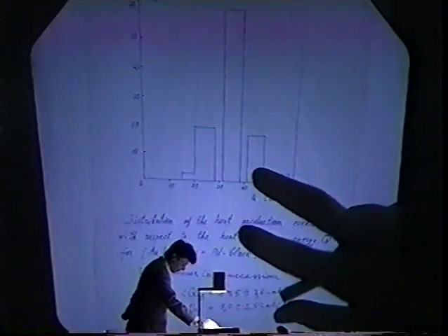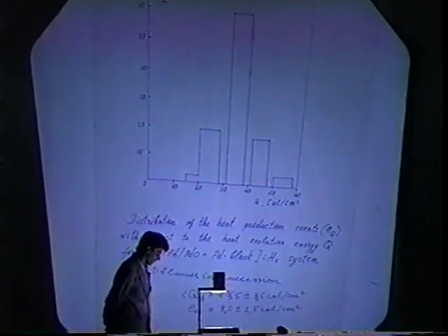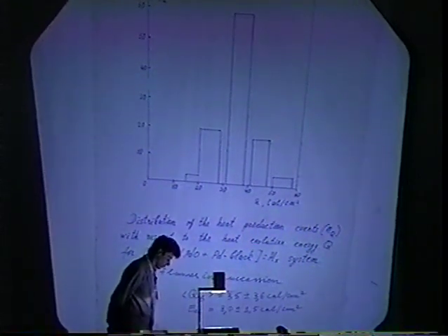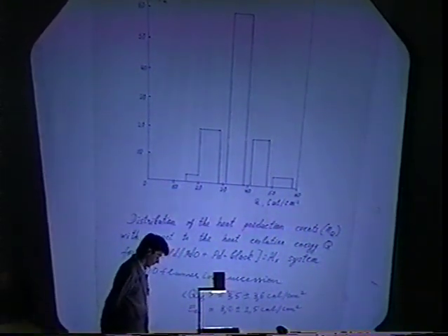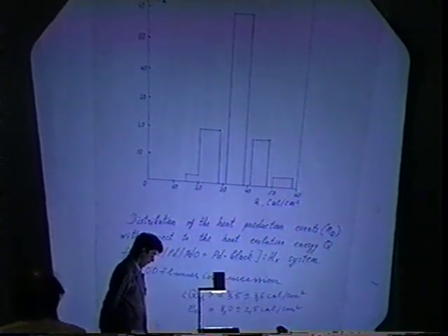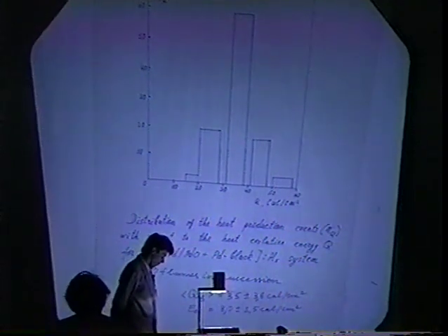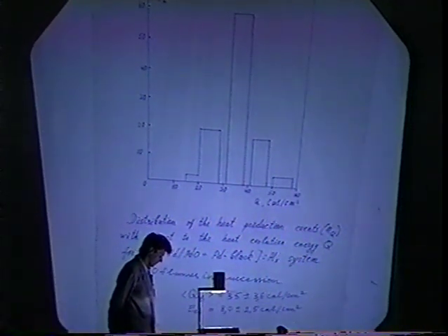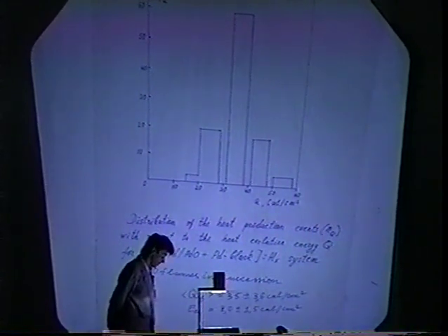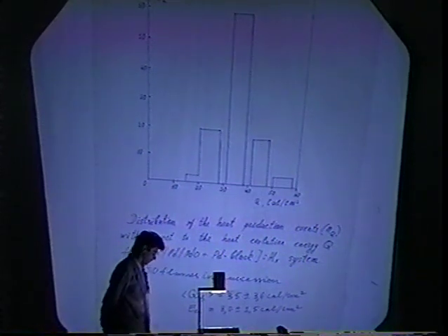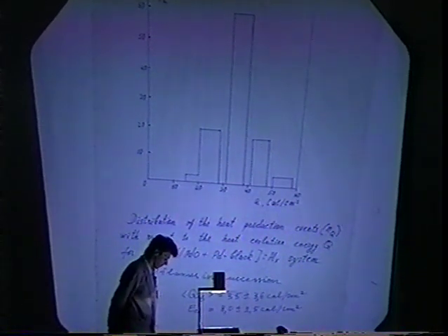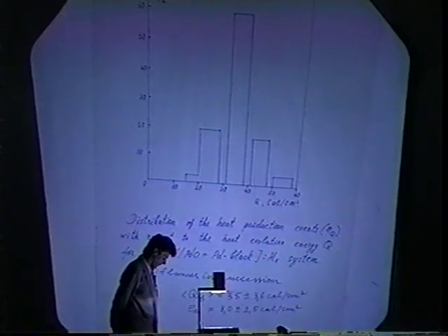The magnitude of the thermal effect can be increased essentially when the specific surface of the heterostructure sample is strongly increased. For this purpose, we use palladium black with particle size of about 1 micrometer, deposited by electrochemical method onto the palladium core surface.